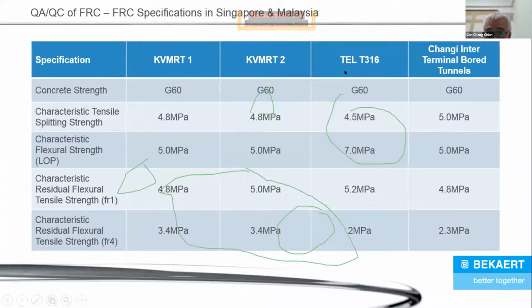And this is Thomson East Coast Line, T316. This is ongoing, currently being precast. They are using 4.5 for tensile splitting strength. LOP is a very high 7. FR1 is 5.2, and FR4 is 2. And lastly, you will see the Changi inter-terminal bored tunnels. Tensile splitting strength is 5. LOP is 5. FR1 is 4.8, but characteristic FR4 is 2.3. So it's slightly higher than the LTA's requirement. So they probably need a higher bending moment as well.